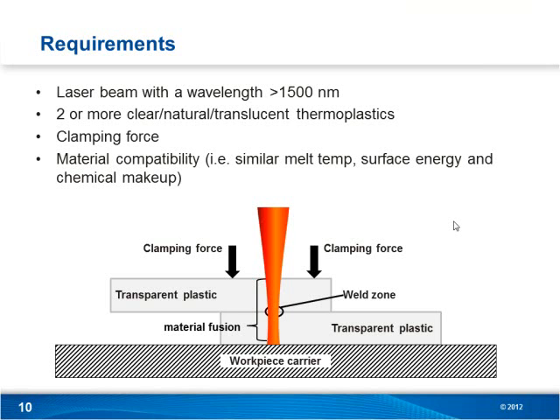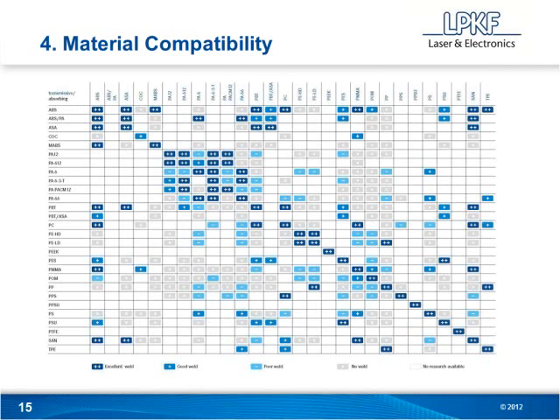We also need clamping force and then material compatibility. So if we're welding two dissimilar pieces of plastic, then the melt temperatures of the two pieces of plastic need to overlap somewhat. They also need to have similar surface energies and similar chemical makeups. I'm going to jump ahead a slide real quick here. If you're not a polymer expert, like I know I'm not, then we do have these cheat sheets for letting you know which types of plastics are going to weld together. Keep in mind this material chart was actually created for regular through transmission laser welding. However, for the most part, these are all going to apply because really what we need is just similar material compatibility.